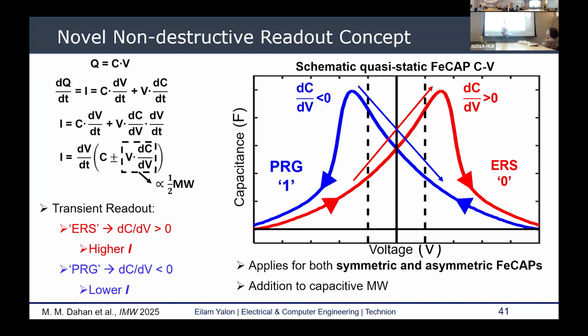So we apply a small voltage below the coercive voltage so that we don't switch the capacitor. And then for a very simple analysis of the transient current, we have the C dV/dt term, the usual displacement current term. In addition, because it's a ferroelectric capacitor and the capacitance is not constant, we have an additional term of the change in the capacitance with time, which we can break into the change of the capacitance with voltage and the change of voltage with time. So when we look at the transient, we have the capacitance term, but in addition, we have this term of change of capacitance with voltage.